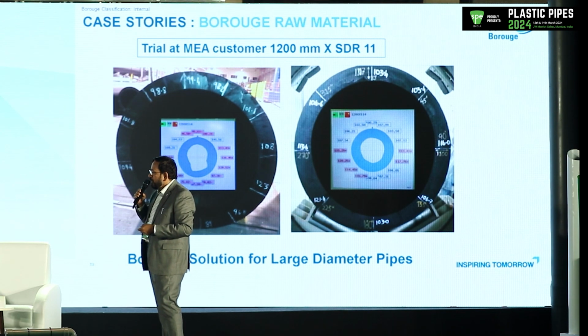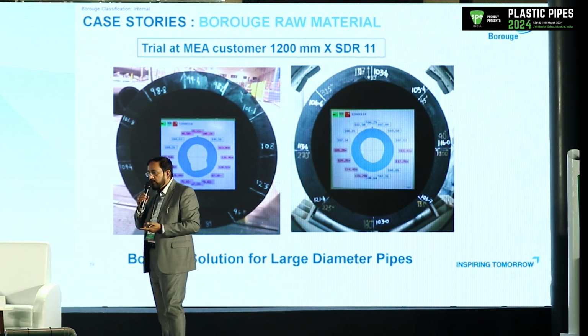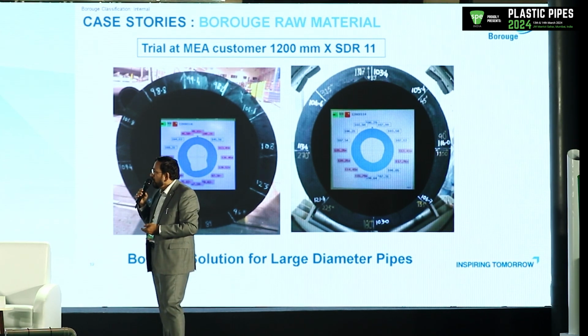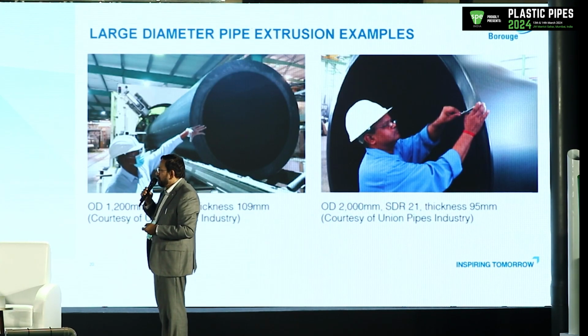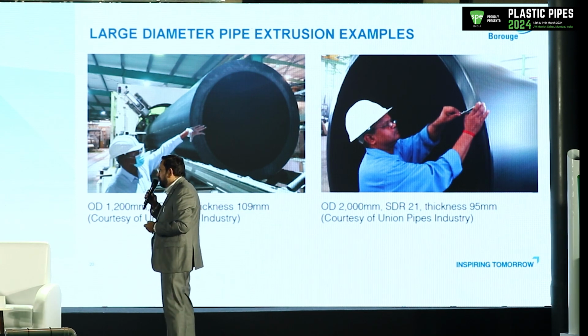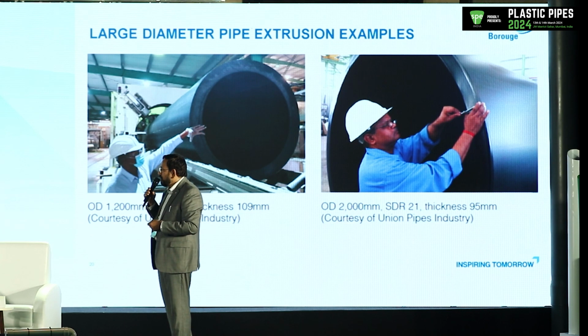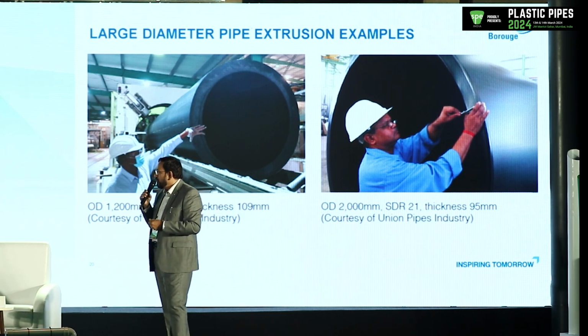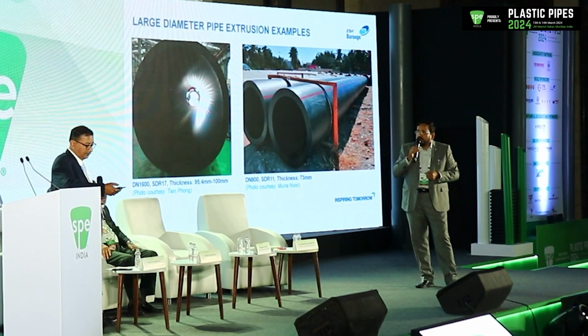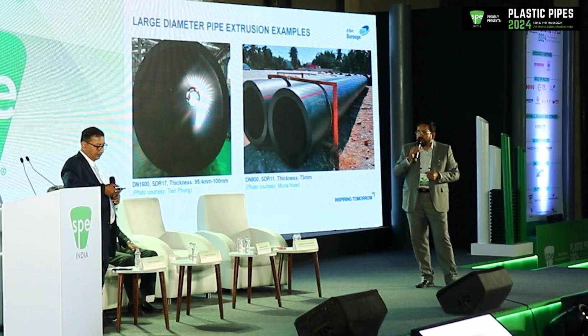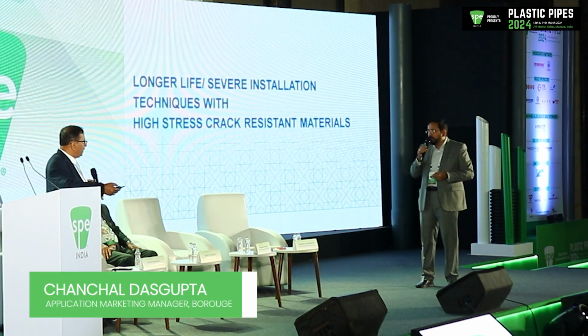Here is an example. If you are not able to maintain thickness, this will happen. But if you use good quality material in probably the same machine, this is what you can achieve. So here are some examples: 1200 SDR 11, thickness is 109. 2000 pipe with SDR 21, where the thickness is 95. Then we have a 1600 SDR 17, thickness around 95 to 100, and DN 800, SDR 11, thickness is 73. So the things are moving.